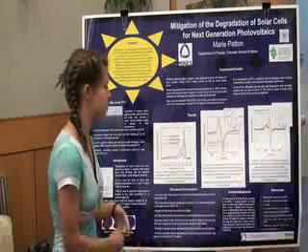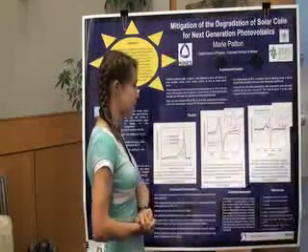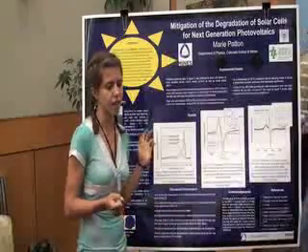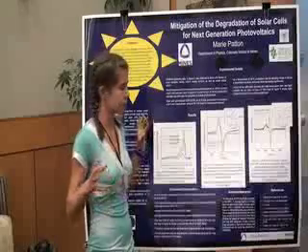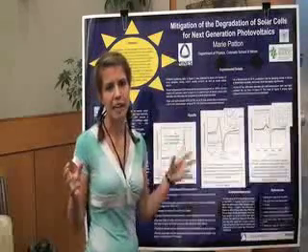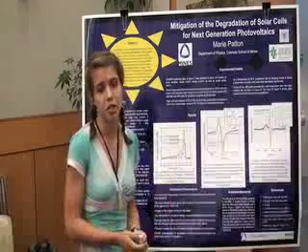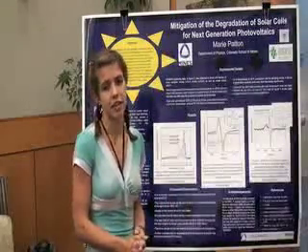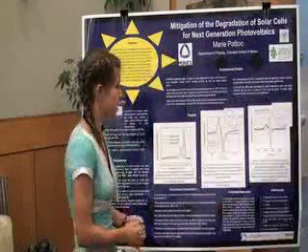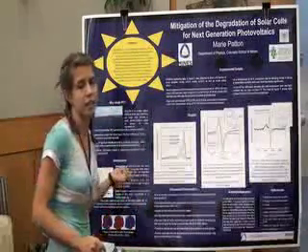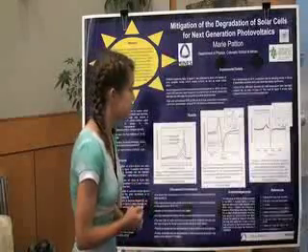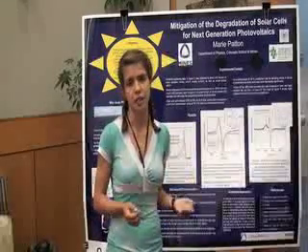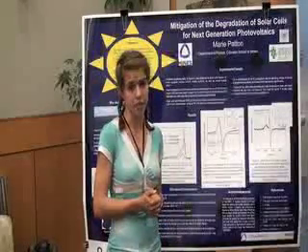The next thing I did was electron spin resonance. It's 2 huge coils of wire that create a magnetic field, and what they do is measure the defects in the samples. The defects really are created from the dangling bonds, which are mostly in the amorphous phase of the silicon. We know it's in the amorphous phase because pure crystalline silicon has little to no ESR signal.